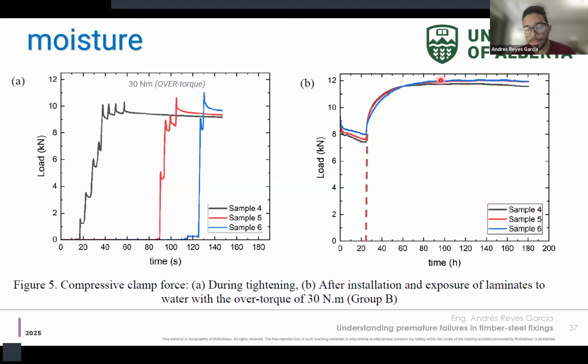Nonetheless, we have a final result of the over stress that is even higher. So we are still at 12 kilonewtons. We expected these experiments, or at least this phase, these samples, to break, but actually we found out that these two factors, over torquing and swelling, at least in these cases, do not sum. So it's not like the more over torque you have, the more is the swelling effect. But because you have more or less a sponge effect. If you have a sponge in your hand and you add some water, the sponge will not increase its volume because it cannot absorb. It's not allowed to absorb.